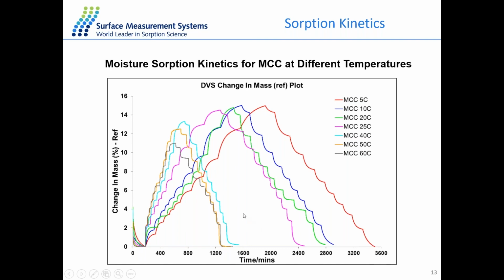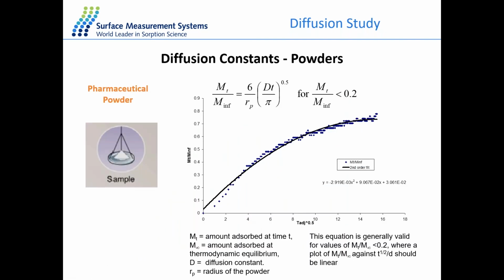And from the DVS data, we can also calculate the diffusion constant for the water molecule at different temperatures. The calculation of the diffusion for water is very similar to the diffusion calculation with thin film samples as introduced in the previous presentation. So we use exactly the same equation here, but in the case of the thin film sample, we use the thickness of the thin film, and in the case of the powder sample, it is replaced by the radius of the powder particles. So we have the mass at time t and the mass at the equilibrium state, and we also have the duration for the sample to reach equilibrium and the radius of the powder. Then we can get a fitting line of the curve, and from the slope, we can calculate the diffusion constant of this powder sample at certain RH conditions.